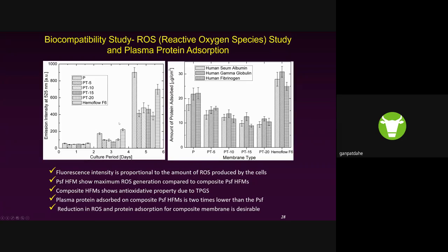So you can see the reactive oxygen species generation. We also use a commercial membrane just as a comparison. This Hemoflow F6 is the commercial membrane, and we also found quite encouraging results. This is a very exciting result, where in this case, the lower the reactive oxygen species, the better the membrane. You can see we have done the cell culture study for 5 days.